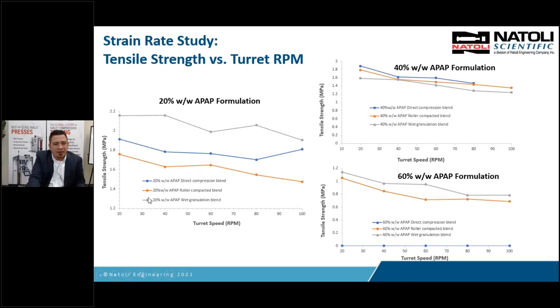And you'll notice that the gray is the wet granulation blend, the blue is direct compression, and the orange is roller compacted. What are we looking at here? We're looking at the tablet strength as a function of the turret speed. So as we increase speed, what happens to our strength? You'll notice that we are dropping in strength. We started, let's say, almost 2.2, and ended a little bit below 2. So, you know, we're losing over 10% strength from slow speed to high speed. And we're following a similar trend for the others as well.